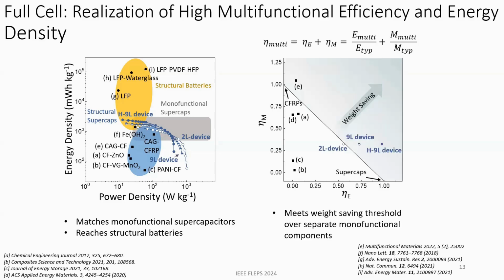And then next is the multifunctional efficiency. So this looks at how good it is compared to using two separate monofunctional components. So we have a baseline electrical and mechanical value. And if these together add up to more than one, then the weight saving is worth using this device over the two separate components. So as you can see, prior works don't meet it except for this one, and they all skew to high mechanical strength, but no electrochemical performance. But our 2-layer device is able to meet this threshold with our 9-layer devices exceeding it.